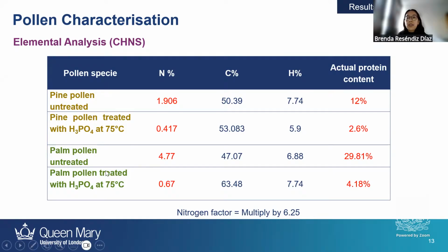Same for palm pollen, it was 29.8%, and after the treatment, we reduced it to 4%. So actually, the treatment was removing almost completely all the proteins here. To get this, I multiply the nitrogen by the factor 6.25. And here also in the carbon percentage, there was an increase, and also for palm pollen.